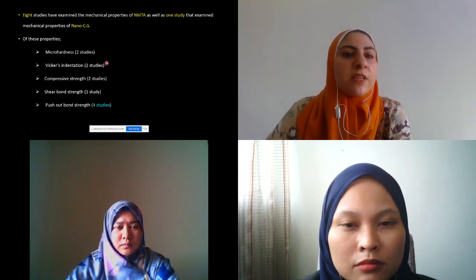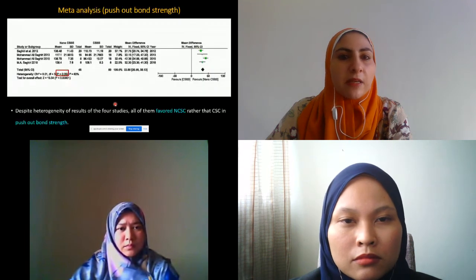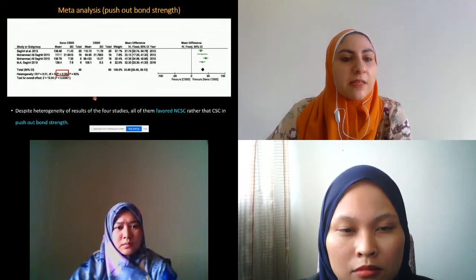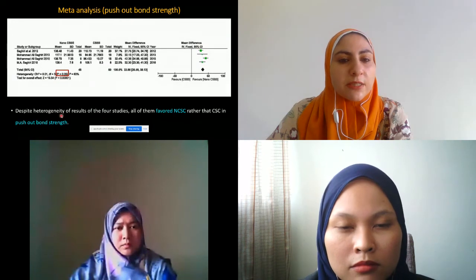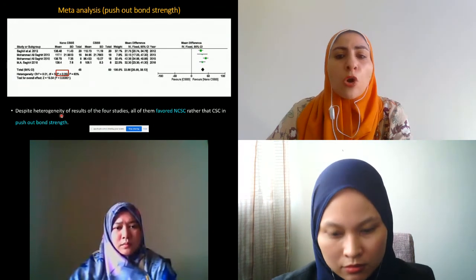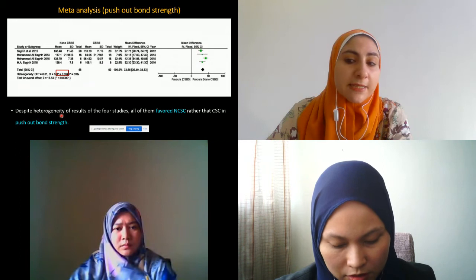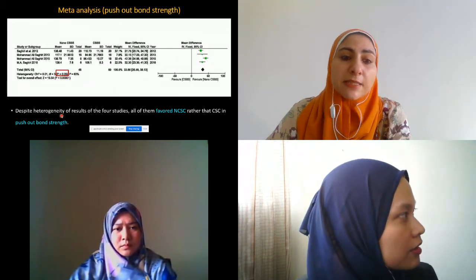8 studies have examined mechanical properties of Nano-MTA, and 1 study examined the mechanical properties of calcium silicate cement. Of these properties were microhardness, Vickers indentation, compressive strength, shear bond strength, and push-out bond strength, which has 4 studies and was selected for the meta-analysis. From the meta-analysis, despite the heterogeneity of the results of the 4 studies, all of them favored nanocalcium silicate cements rather than calcium silicate cements.